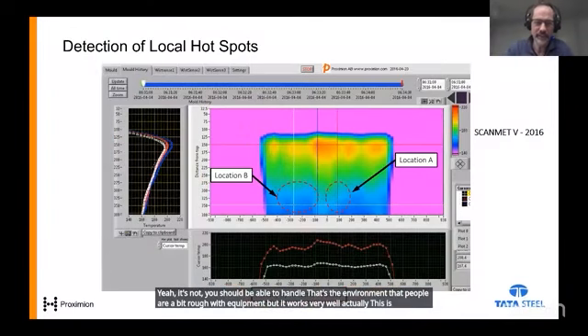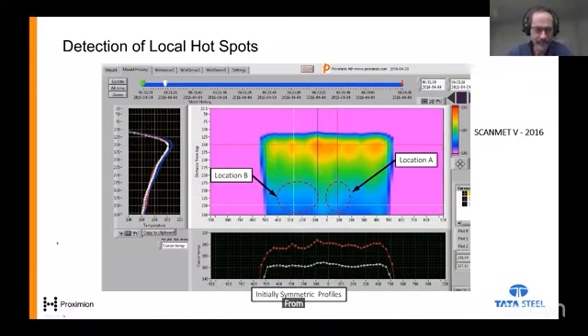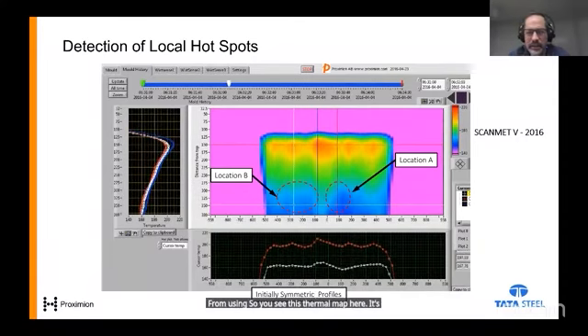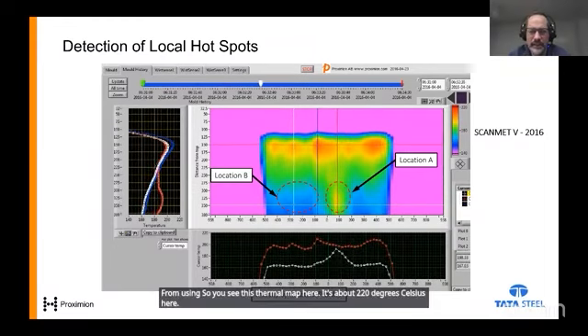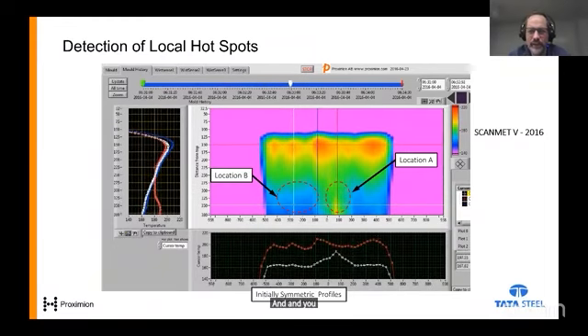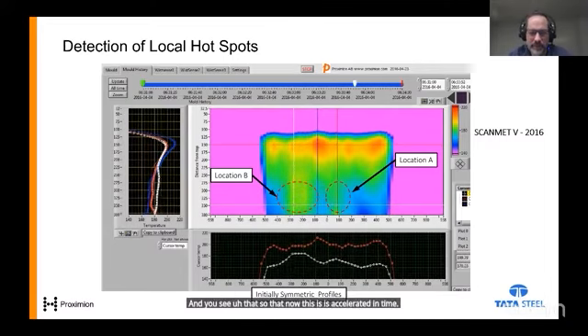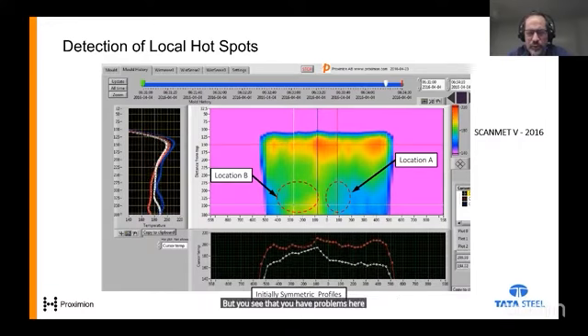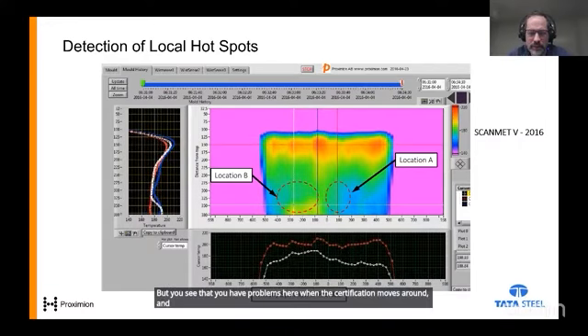This is just an example of what you can see from using it. You see this thermal map here. It's about 220 degrees Celsius, and this is accelerated in time, but you see that you have problems when the solidification moves around, and this could be a case where you could have a breakout, for instance. You might think steel is one thing, but there are many different steel grades, and some are very difficult to cast.